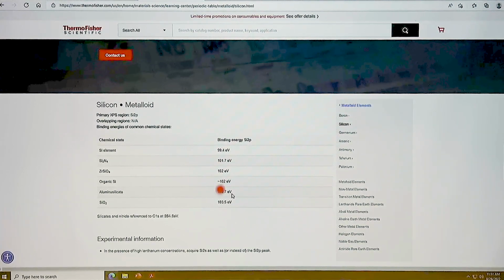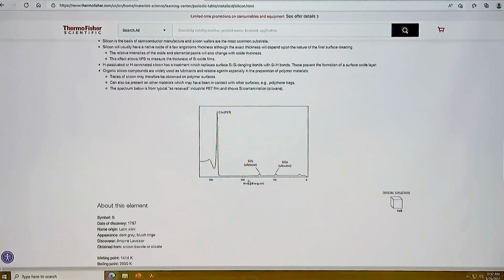Yeah, this is basically an example of an organic silicate. It's 102, and 103.5 is for silicon dioxide. But we need to identify the other aspects of the silicon as well. Out here, it gives two different peaks for siloxane, so it's not always straightforward. We have to figure things out, and check for other elements as well, because sometimes some elements overlap. That test was only for one particular area and not for the whole thing. So we need to redo the analysis with deeper and longer scans to get good results.